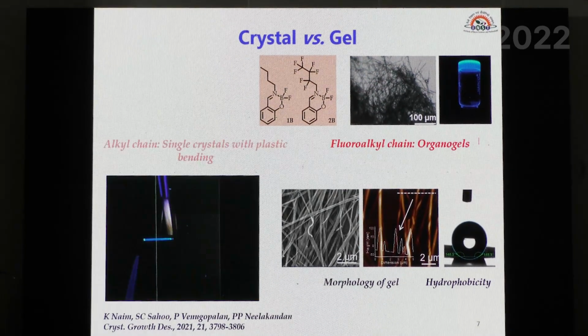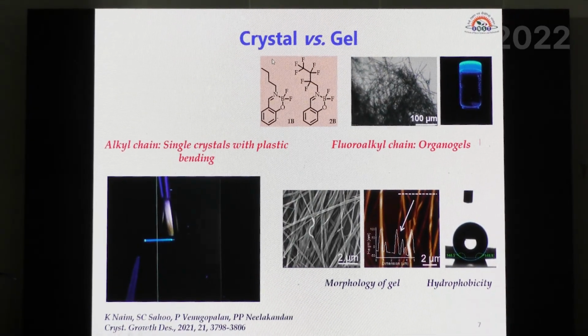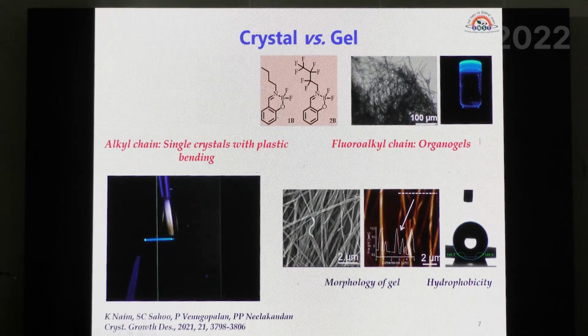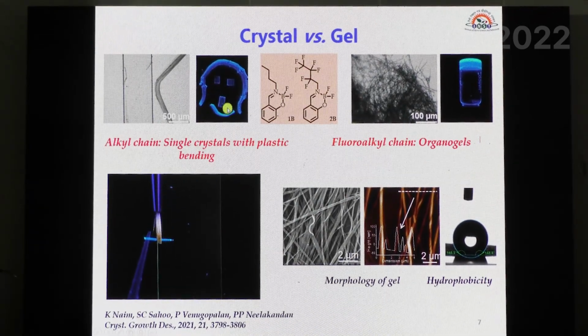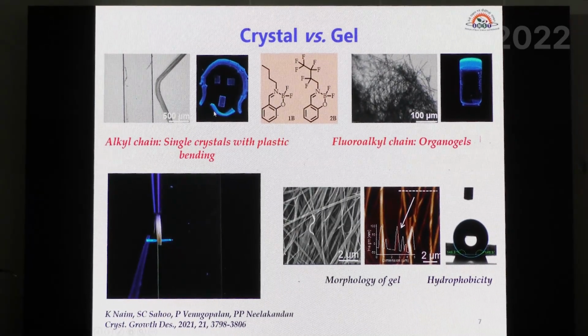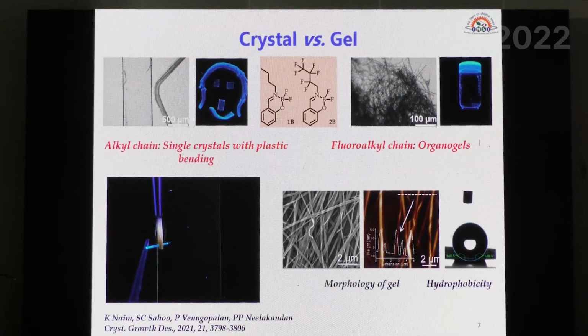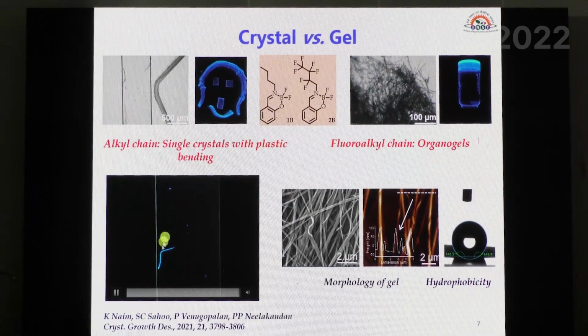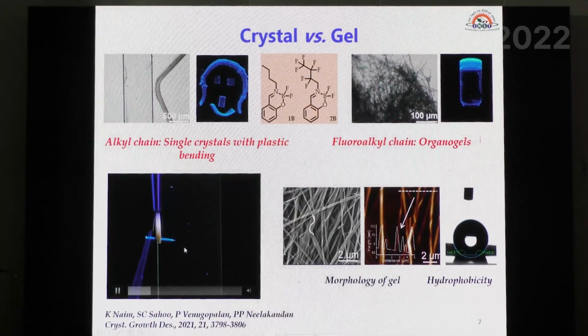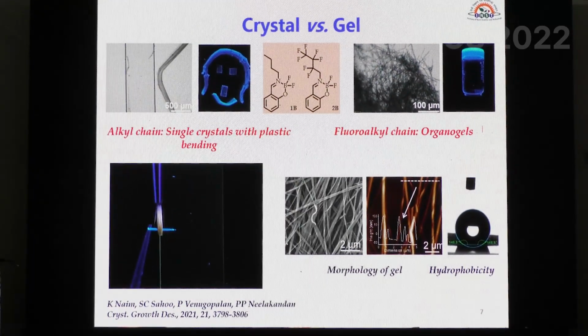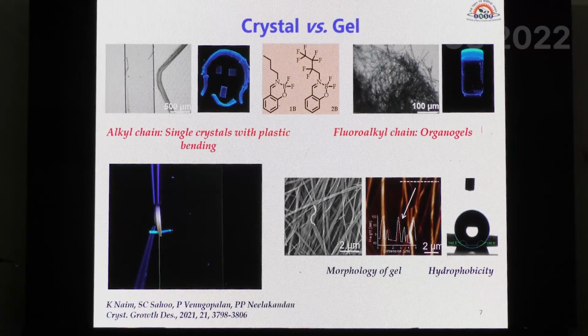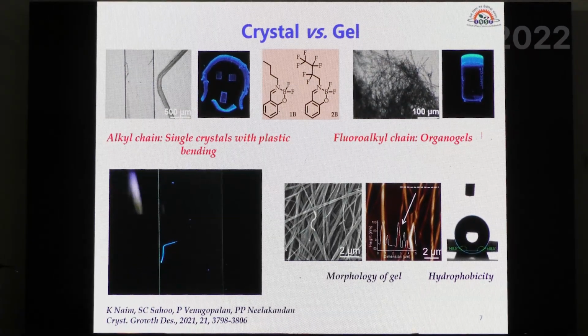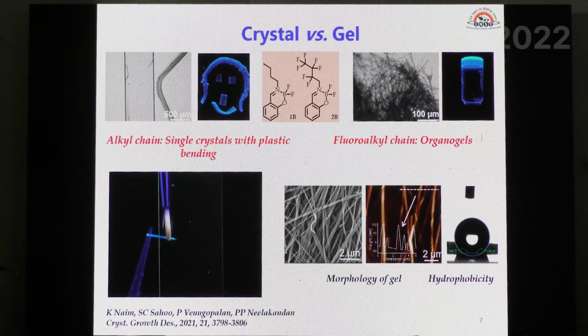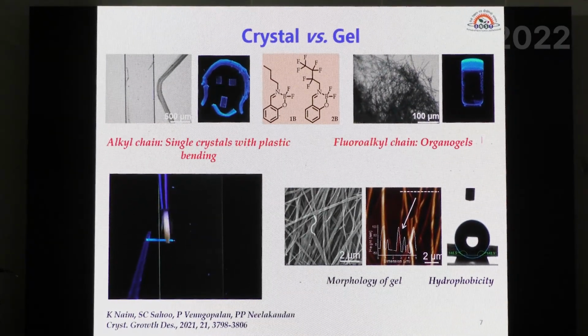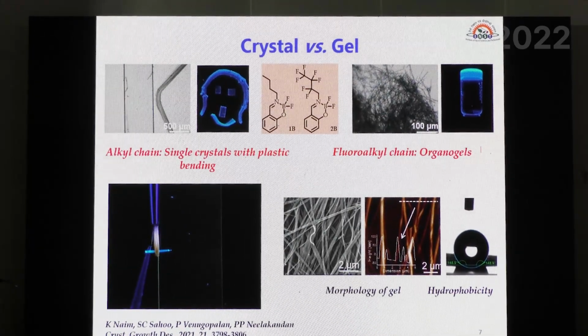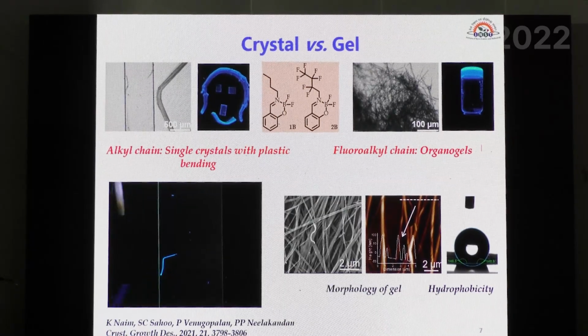But on the other side, when we have these compounds with the alkyl chain, you can see that they form single crystals, and the interesting part was that they form flexible crystals. As you can see in this video, this is a crystal of this compound, and we have put it on a glass slide and we are bending it using a brush and the tip of a pipette. When you do that, they bend, but at the same time they don't break. They retain that bent nature, and we have analyzed them through single crystal analysis, they don't lose the crystallinity after the bending process. And they are highly fluorescent, so that can have applications which I will show you later. Next.